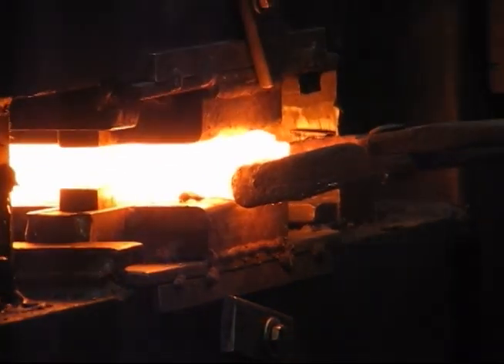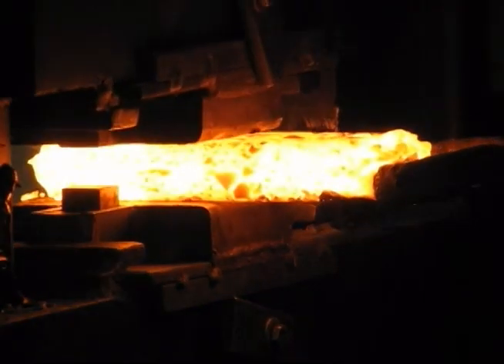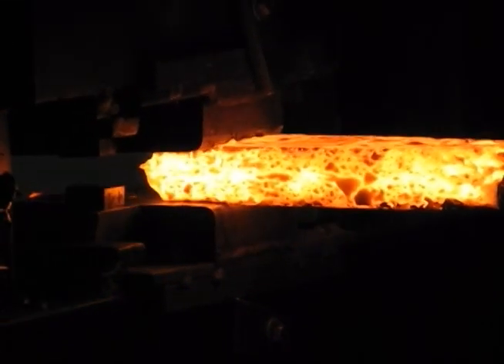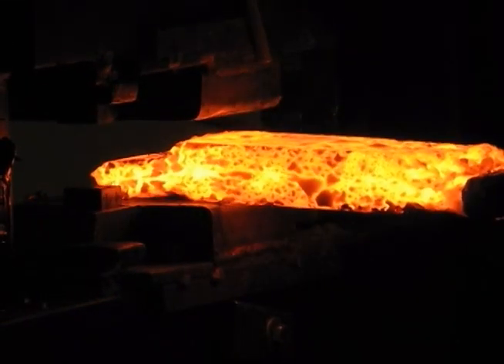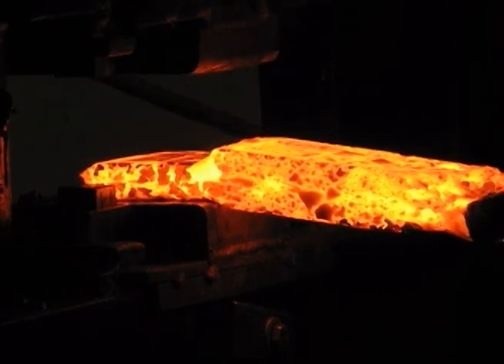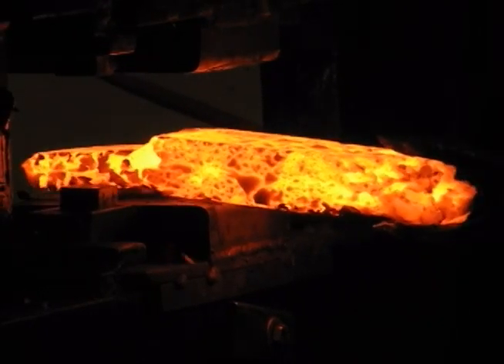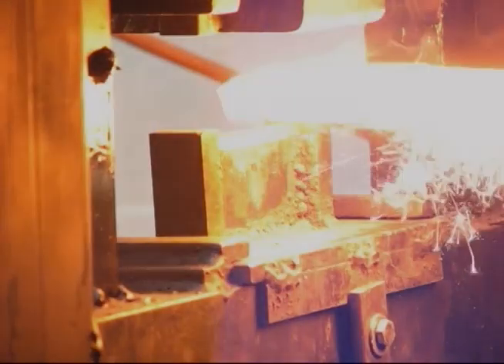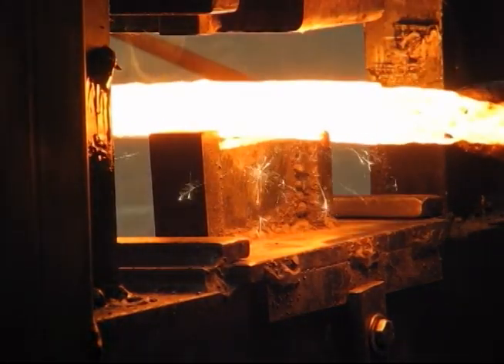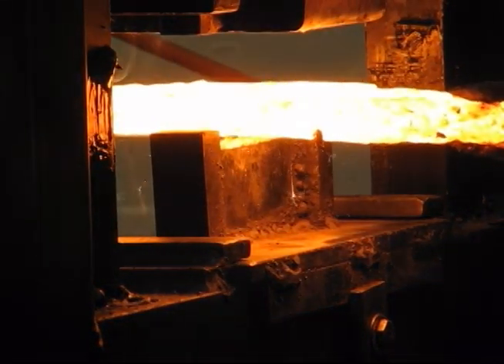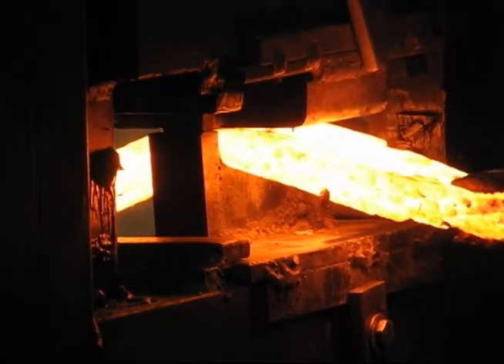This particular bar of steel forged very nicely under the stress of the press, reducing in size without evidence of cracking or delaminations, even when the total thickness was being reduced in half during a single pass. Notice the sparking. Who said that a propane forge can't get hot enough to burn metal?